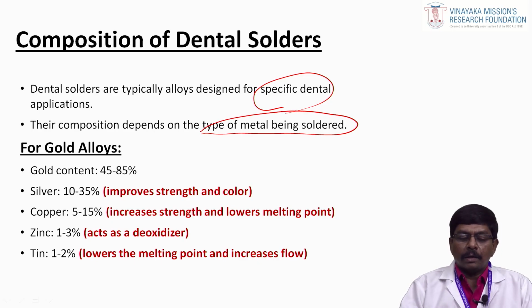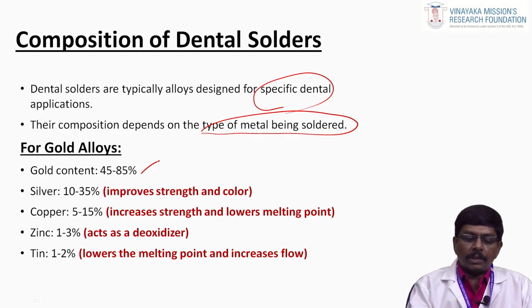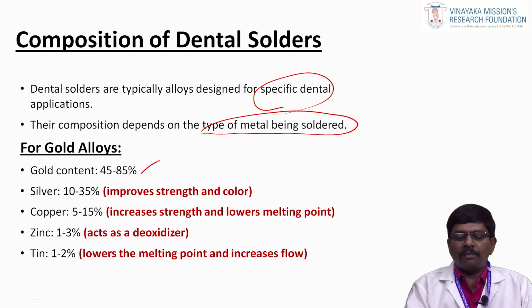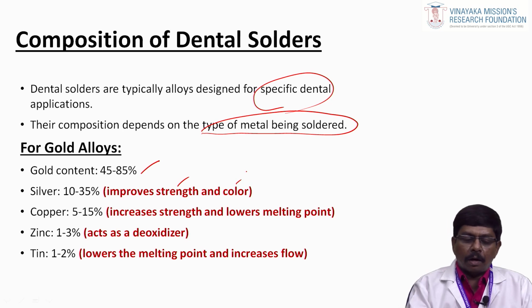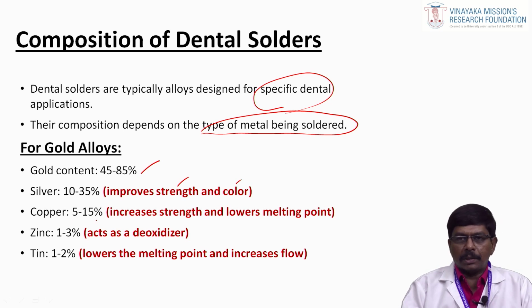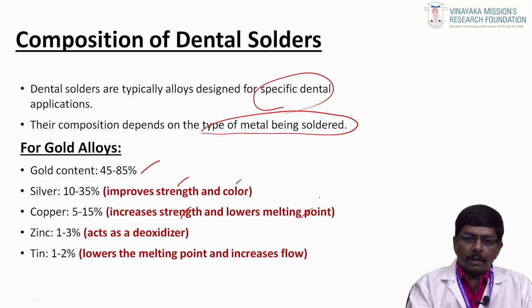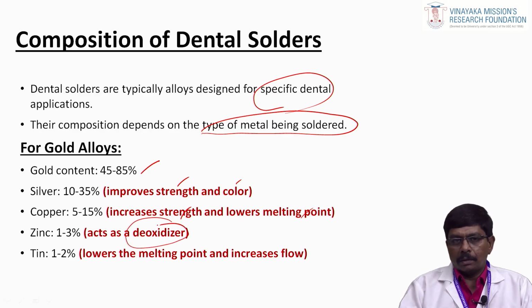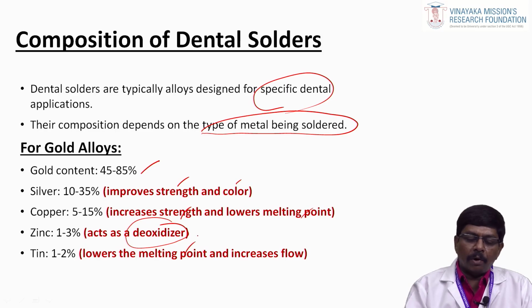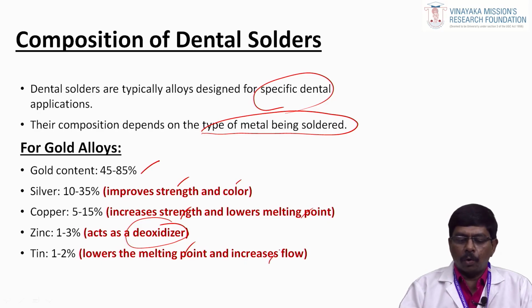For gold alloys, the gold content is 45 to 85 percent. Next is silver, with 10 to 35 percent. The role of silver is to improve the strength and give color to the metal. Next is copper, with a content of 5 to 15%. It provides strength and lowers the melting point. Next is zinc, 1 to 3%. It acts as a deoxidizer. The lowest content is tin, 1 to 2%, which helps in lowering the melting point, and it also increases the flow of the solder.